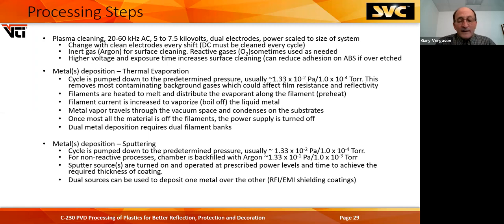In sputtering, we've got a little bit of differences here. You pump down to your predetermined pressures. In some cases, depending on what you're trying to do, you're down into the 8 times 10 to the minus 5 torr range instead of the 10 to the minus 4. For a non-reactive process, the vacuum chamber is backfilled with argon, usually to about a micron chamber pressure. Sputter sources are turned on, operated at the prescribed power levels and time to achieve the coating thickness and uniformity that you're looking for. With dual sources, you can either deposit at the same time from opposite ends of the chamber to shorten the cycle time, or you can deposit different materials between the two. And we do a lot of different material coating here with RFI/EMI shielding coatings.